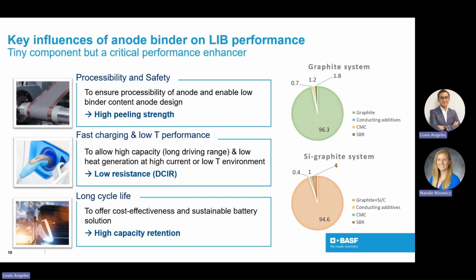In particular, we also look at peel, and this is extremely important for cell manufacturers as they are scaling up on a gigawatt hour scale, making sure that the processability is easy to work with. And then you look at electrochemical properties, and they're important because they impact the lifetime of the battery and also the overall safety of the battery. So we evaluate cycle performance at 500 and 1,000 cycles, and we look at DCIR, or internal resistance, which impacts the ability to charge quickly. That's a pretty common trend in the battery segment. And then also capacity retention, which impacts the longevity of the battery. So all of those factors come together to make a well-performing battery, and the binder is a small but very important part of that.